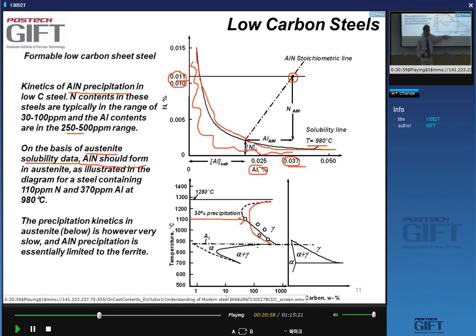So by choosing the coiling temperature right, we can have either a lot of aluminum nitride or very little. High coiling temperatures give me a lot of aluminum nitride precipitated after the runout table in the hot coil, or if I have a low coiling temperature, I can just keep it in solution. And even though aluminum nitride is thermodynamically not very soluble in austenite and has an even smaller solubility in ferrite, because of the kinetics of the precipitation, I can still suppress the aluminum nitride formation.